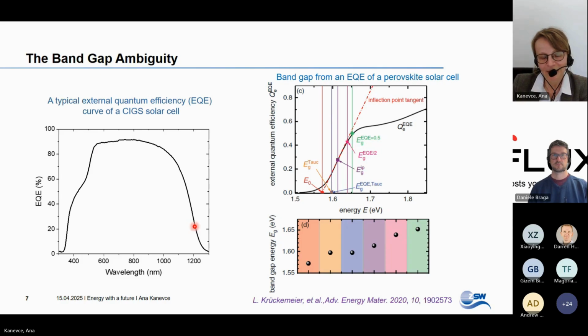Now, historically, we started saying it's a rule of thumb. It was either 30%, it was 50% absolute, it was 50% of maximum quantum efficiency. Then the determination of bandgap evolved to Tauc plots, to Tauc methods. And then in the newest analysis, one uses the inflection point. Here is an example from literature. This is of perovskites. What would be the bandgap value from QE if determined from different methods? And what one sees is actually there is a big difference, right? Here is a 100 millielectron volt difference. So one has to keep in mind when one speaks about bandgap as an absolute and stiff value.